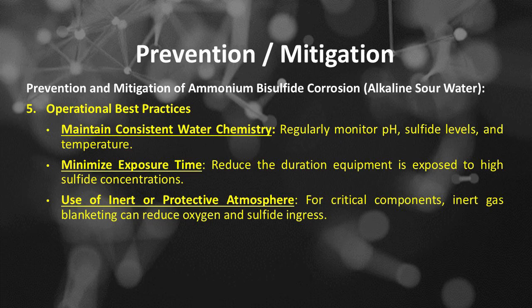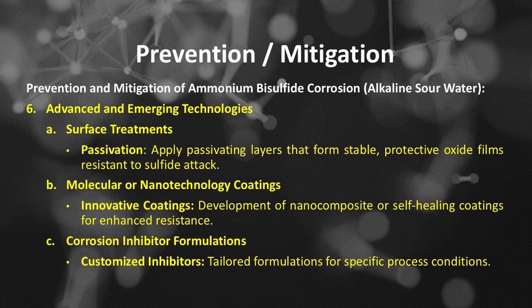Number 5 is operational best practices. Maintain consistent water chemistry, and regularly monitor pH, sulfide levels, and temperature. Minimize exposure time: reduce the duration equipment is exposed to high sulfide concentrations. Use an inert or protective atmosphere for critical components. Inert gas blanketing can reduce oxygen and sulfide ingress. Prevention and mitigation of ammonium bisulfide corrosion in alkaline sour water.